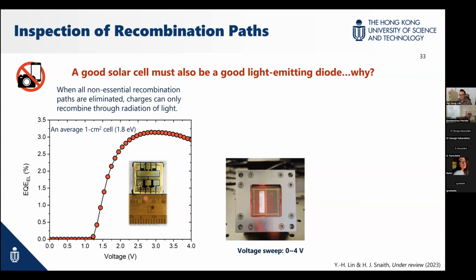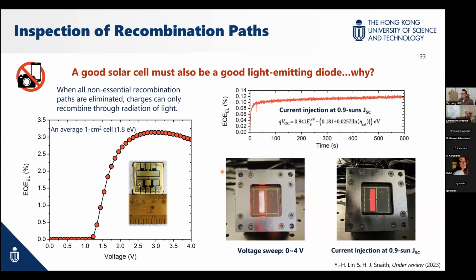But we take a solar cell, which is quite thick. We inject charge carriers. As you can see, we sweep the voltage from 0 volt to 4 volt. You can see it's uniformly emitting, and the line is around 700 nanometer. But something more impressive is that when we apply current injection, that is around 0.9 times JSC.